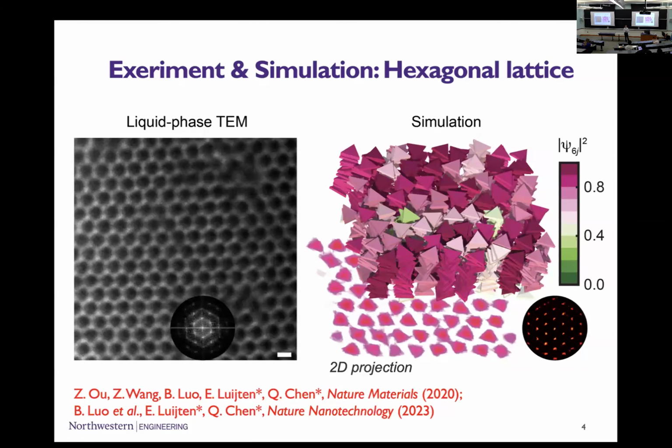But it's still challenging, because if I give you a triangular particle and I say two triangles are meeting, then of course that is very different from two spherical particles meeting. In what orientation are they meeting? So it's still pretty complicated, but we were able to develop an effective potential between every pair of these nanoparticles, put it in a Monte Carlo simulation, and we saw the same thing.